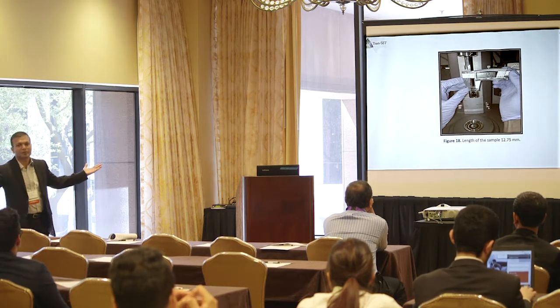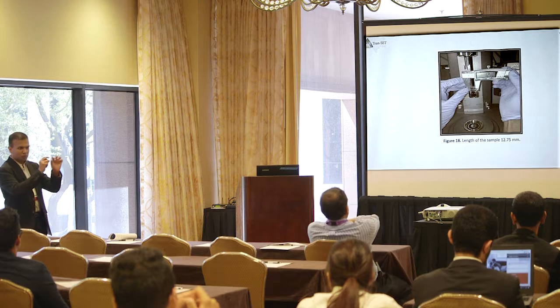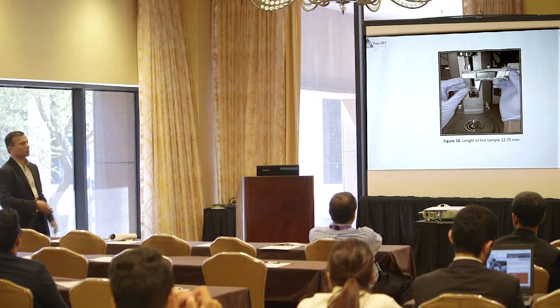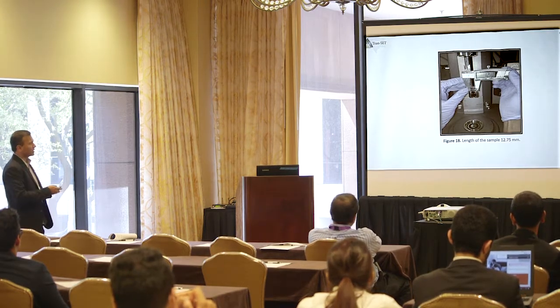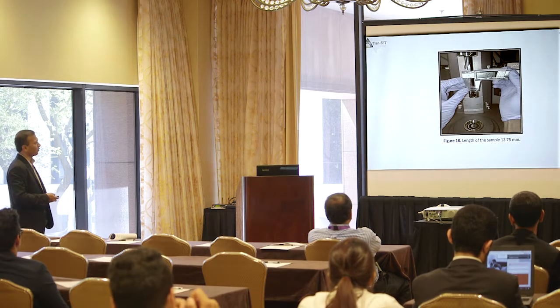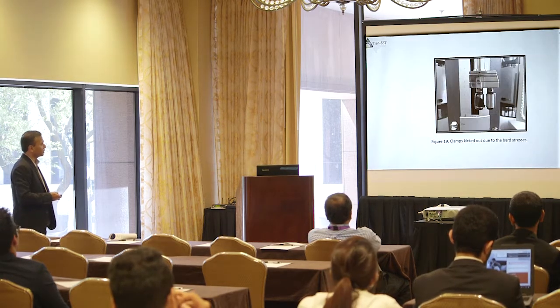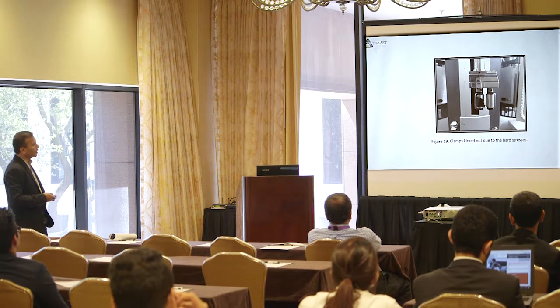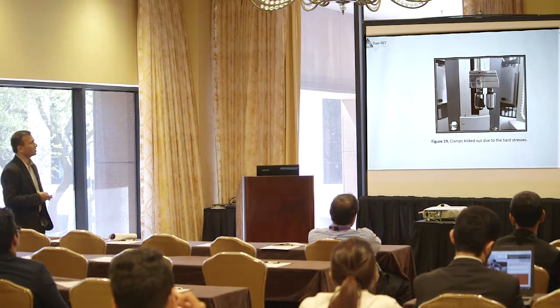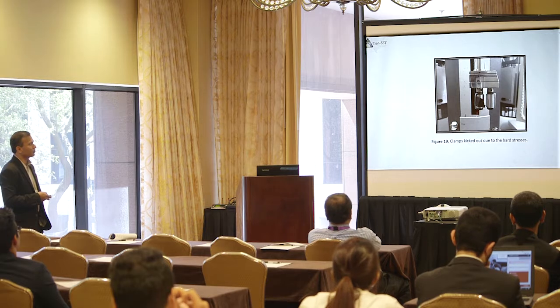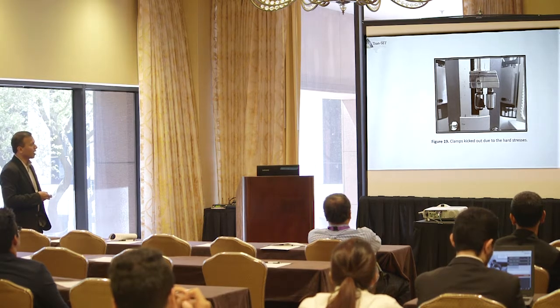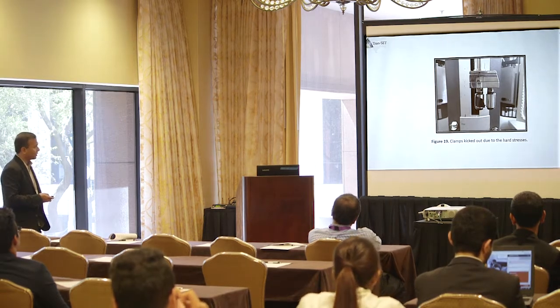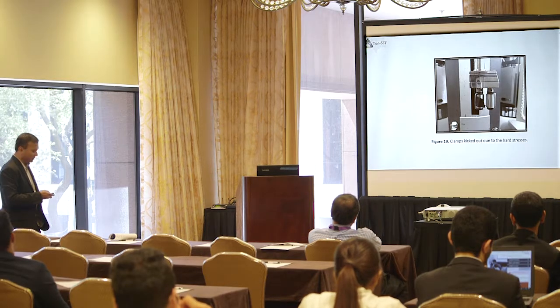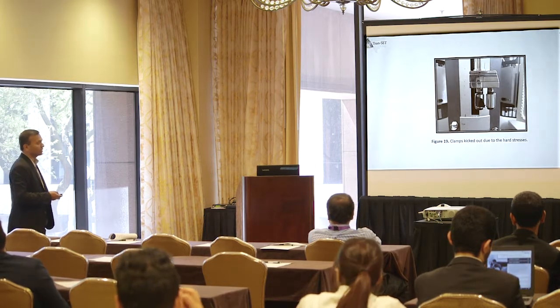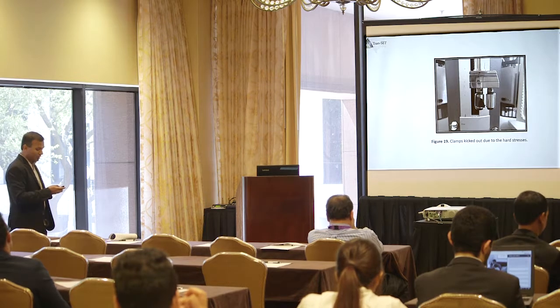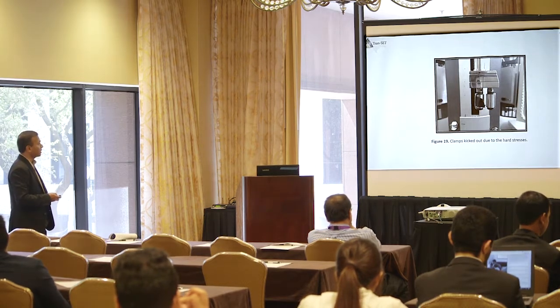So even if you prepare long samples, it will work, the force will act between the two clamps. And that clamp distance is fixed because you have two holes for each of the samples. This is what happens if you put very big samples, and this is a very wide thickness. The width is very high, and if you do that at 4 degrees or 0 degrees Celsius, the binder is really stiff. So it came out.